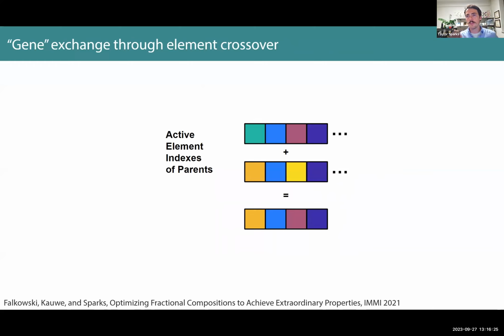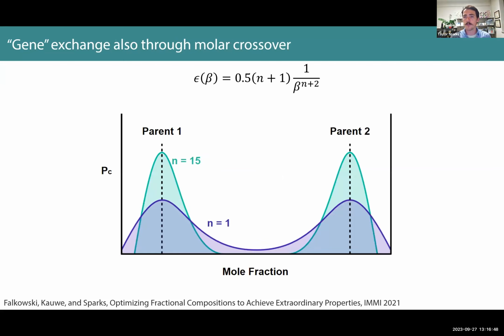It's easy, for example, if you're combining two different materials and they both have tantalum in the formula, clearly the offspring is going to have tantalum, barring exceptions for mutations. But what if one parent has oxygen and one has sulfur? Do you make it an oxide or a sulfide, right? So you have a lot of flexibility in how you can tune that. You can make it so that the parent that had a higher fitness value is more likely to retain its chemistry, right? So these are all tunable hyperparameters in your genetic algorithm.